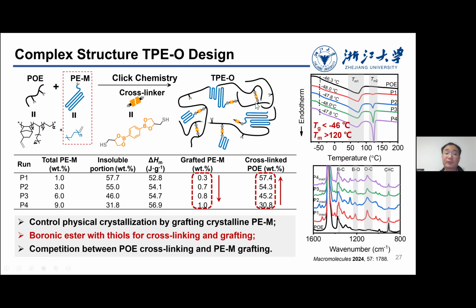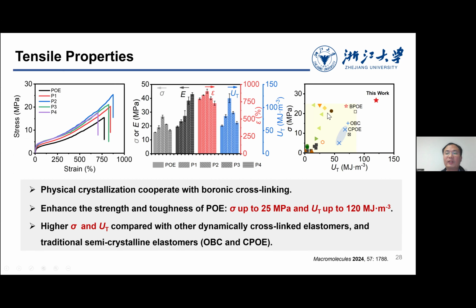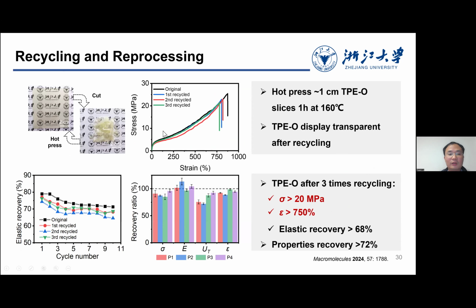So there is a competition between the cross-linking and the grafting. By doing this, we can tune the crystallization and the cross-linking at the same time. And you can see here we can have a low glass transition temperature and also a high melting point. And in this way, we can develop a much higher performance polyolefin elastomer. Here we can have this performance. They exceed almost all the commercial products and the products we just saw in the previous slides. And they can also be reprocessed. For example, here we can still reprocess several times, and they can even be transparent after recycling.